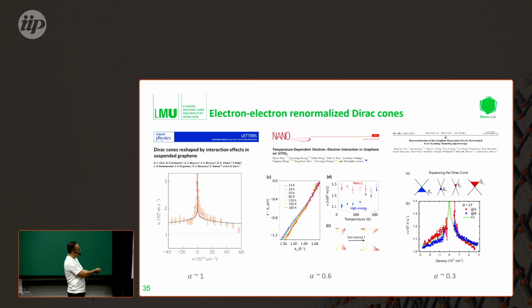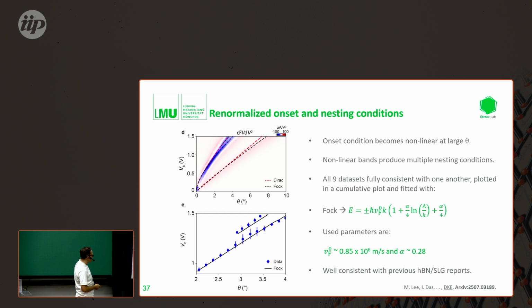So these were also hBN encapsulated devices, a very similar dielectric environment in which they did the measurements. It's also a tunneling spectroscopy measurement, so we found very similar numbers to what they have found before.